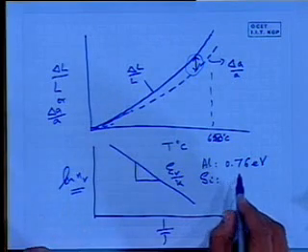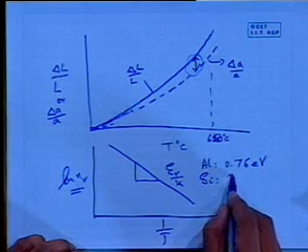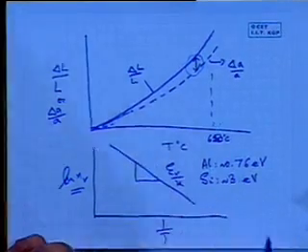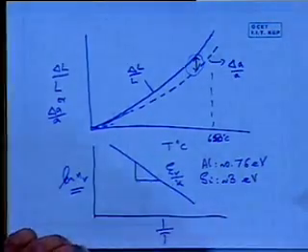On the other hand, in the case of silicon, we require much higher values if you do a similar kind of experiment, and it's of the order of about 3 eV. These are all approximate numbers. I don't recall the exact values, but 2 to 3 eV is the kind of values we see. You see, one is covalently bonded and one is a metallic bond. So there are differences that come about even from bonding, in what energy is required to create the vacancy.